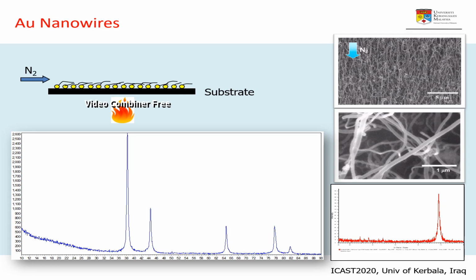The figure at the bottom right-hand side shows the observed X-ray diffractogram when we did X-ray diffraction measurement using the conventional technique. Clearly, there is only one strong reflection detected, which was confirmed to be from the substrate. By comparison, there are several extremely weak reflections, which possibly come from the nanowires.